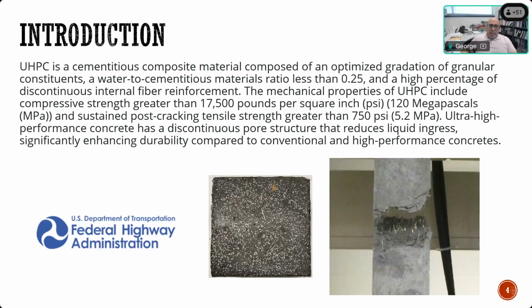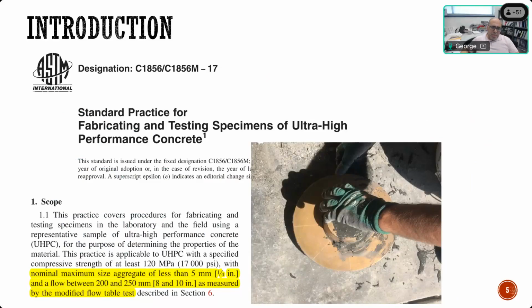The compressive strength is also high, and that's pretty much a byproduct of having optimized gradation. So once the mix is dense in terms of particle packing and has very little void, it also helps the compressive strength. So this is the definition by the FHWA, and before that there was the first ASTM standard, done in 2017. That's ASTM C1856. Up till now, that's the only ASTM standard for UHPC that describes how to fabricate a specimen and how to test them to make sure the properties are met. They also add to the definition a little more information, saying the nominal maximum aggregate size is less than 5 millimeters or a quarter inch. So UHPC doesn't have any coarse aggregate. It's only sand and all the powder material.